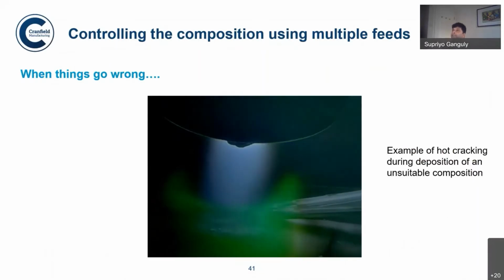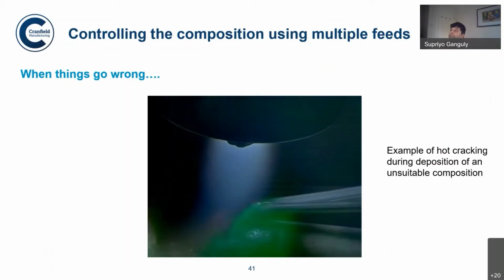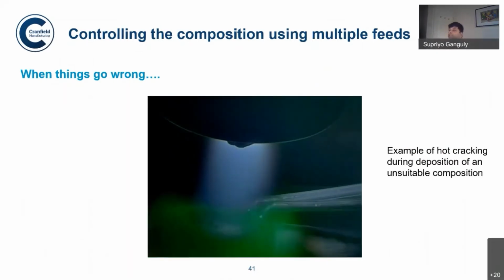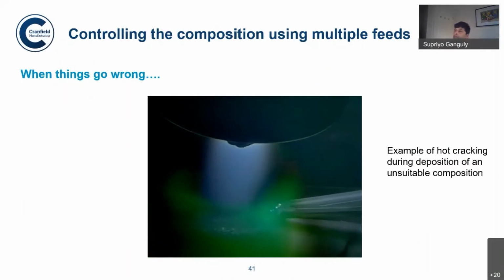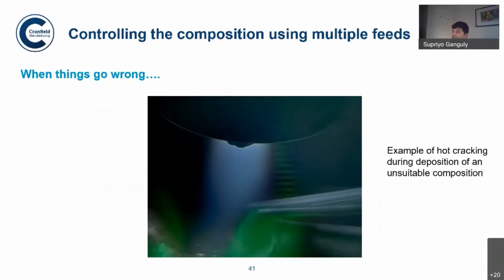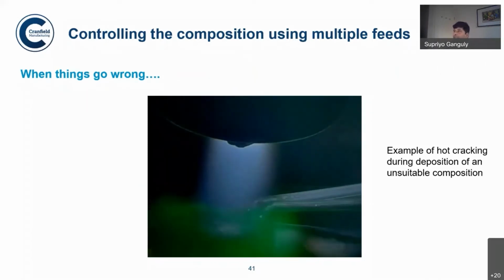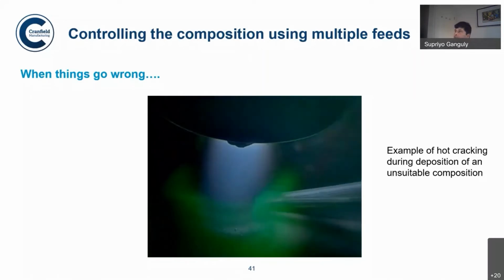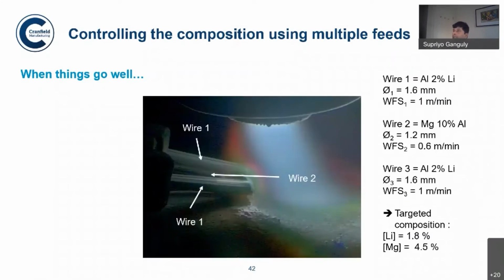that wires are being added, but this is an example where it goes wrong. Basically, you will see that there is a crack formation that happens during this process. Whereas when things go right, it can be quite nice actually. Then the deposit can be built with a lot of integrity, without much formation of cracks or internal defects in the deposit.